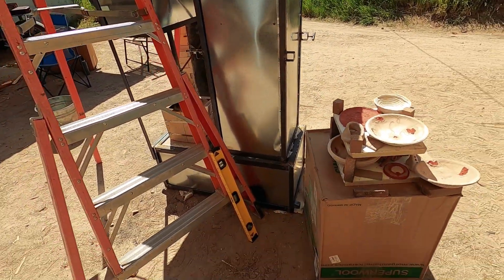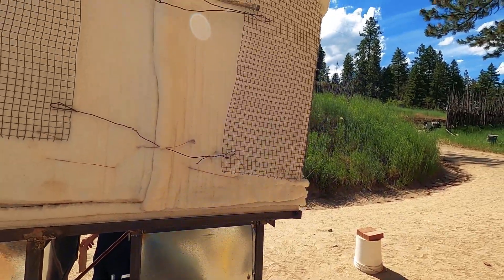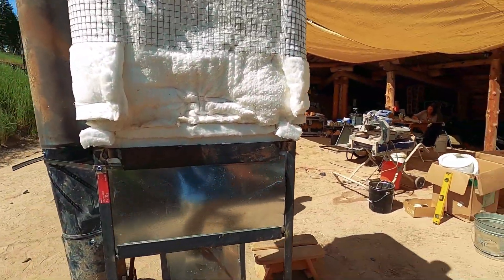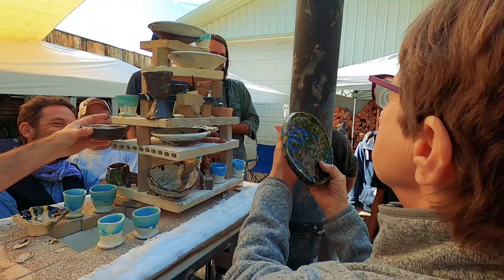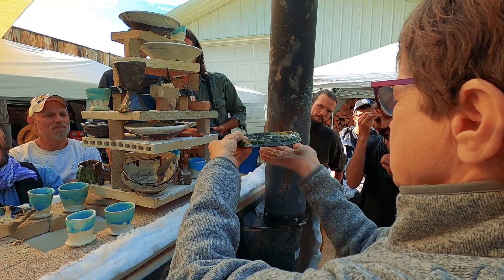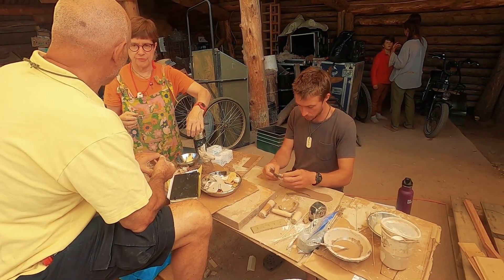This is our third low fire. We got one high fire done in an experimental kiln yesterday that was cone 9 on the bottom, cone 6-7 on the top — way more even than I had anticipated. One of the kilns was cone 04, about 1,945 degrees Fahrenheit, around 2,050 on top, and that was the first experimental firing in a brand new kiln design for all of us. I'm very excited about the rocket-fired kiln. The fact that we achieved high-fire temperatures with just a little bit of wood and zero smoke is totally revolutionary.